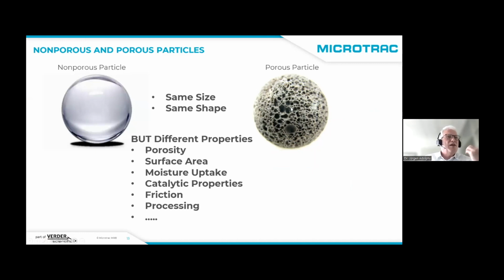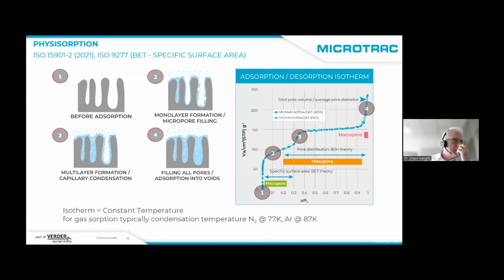The name says already porous, so we are interested in the pores of these particles. Pores are determined by the pore size per volume. And of course, they also offer a much higher surface area compared to a non-porous particle. One of the techniques we use is the so-called gas adsorption technique, or sorption technique. We work at a constant temperature, typically at cryogenic temperatures. For gas sorption, we take nitrogen as the gas and keep it at liquid nitrogen temperature, which is 77 Kelvin or minus 196 degrees Celsius.